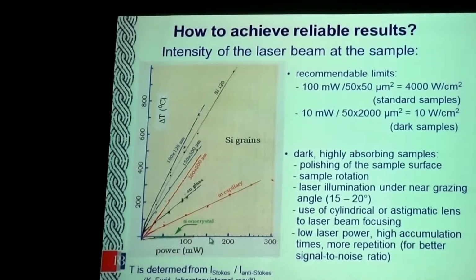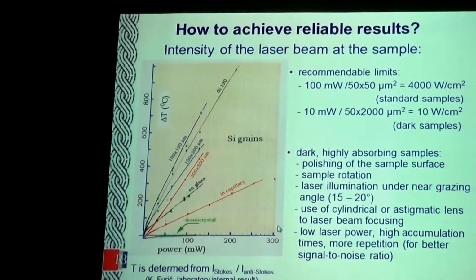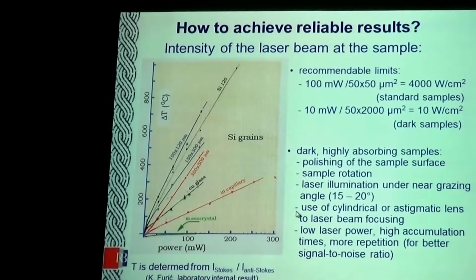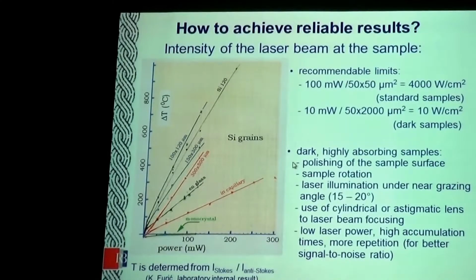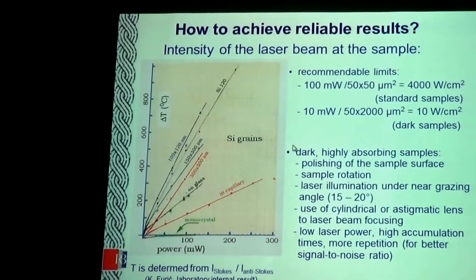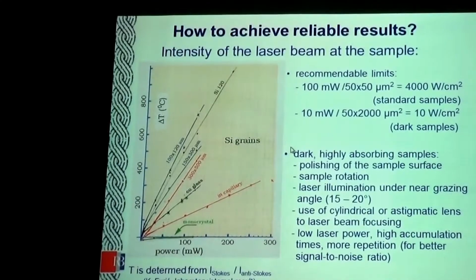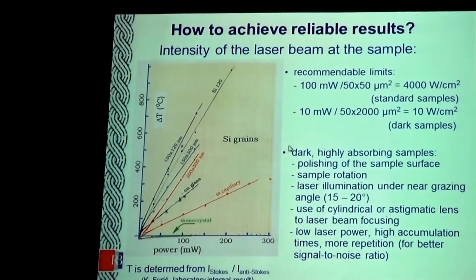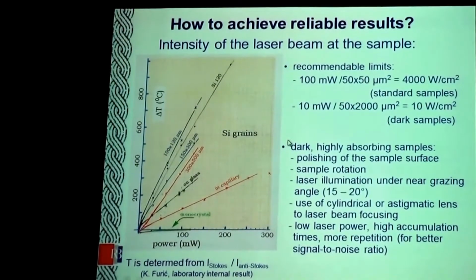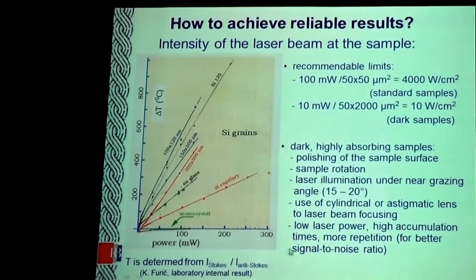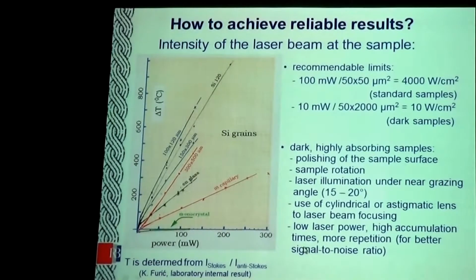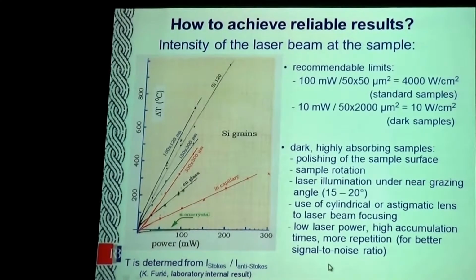And we can avoid such a problem. Partially it can be avoided by polishing the sample surface. We can rotate the sample. We can use, of course, low laser power, but then you will have a lower signal. However, if you use high accumulation times, then you still can get a signal.